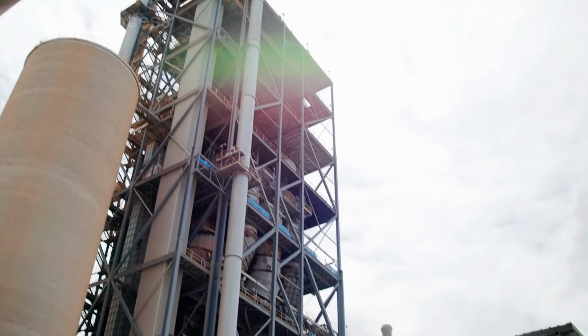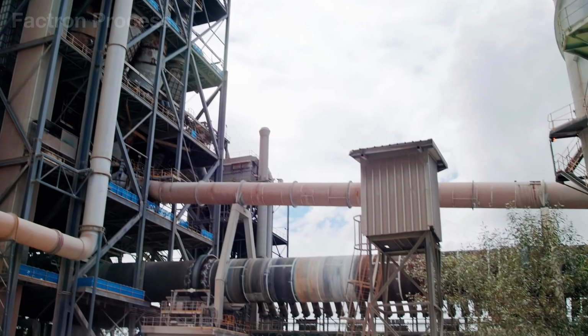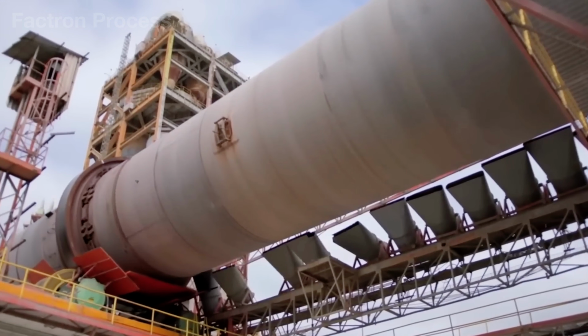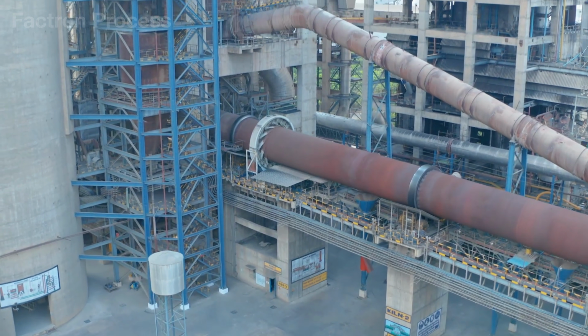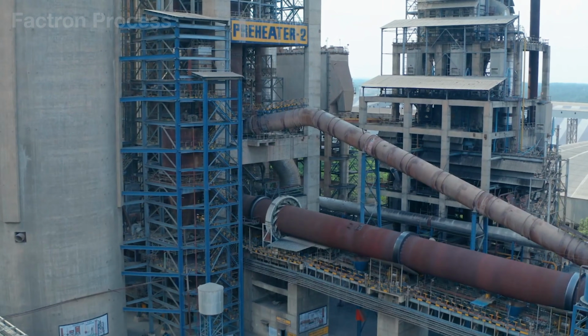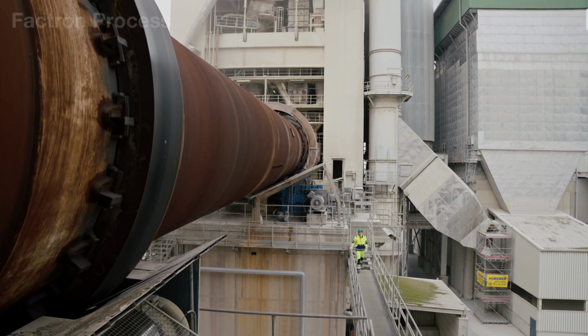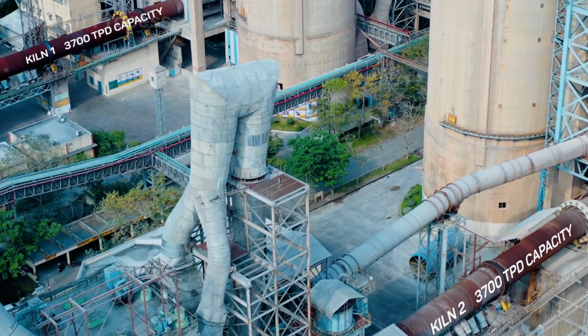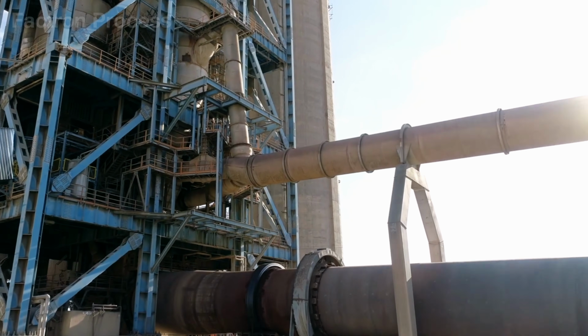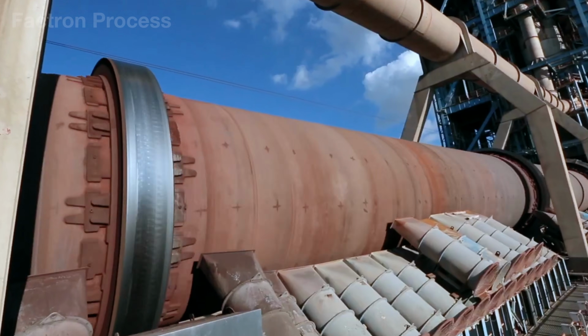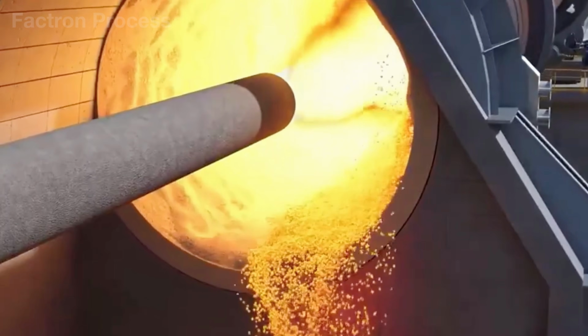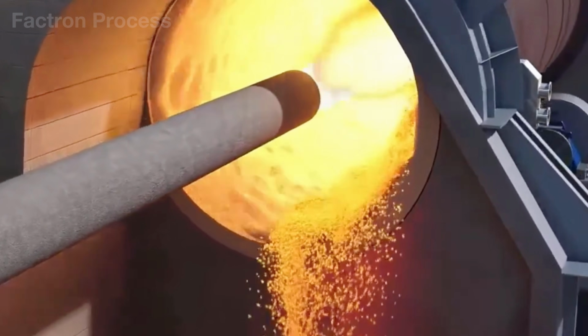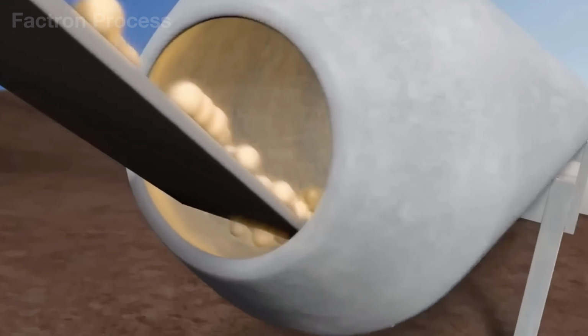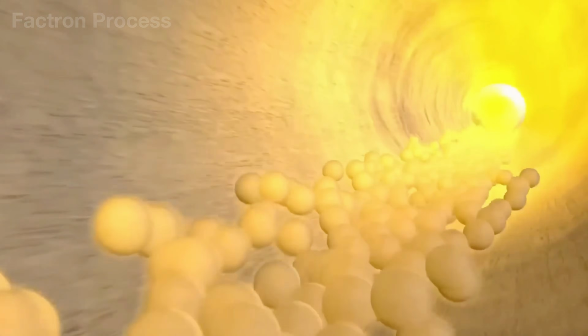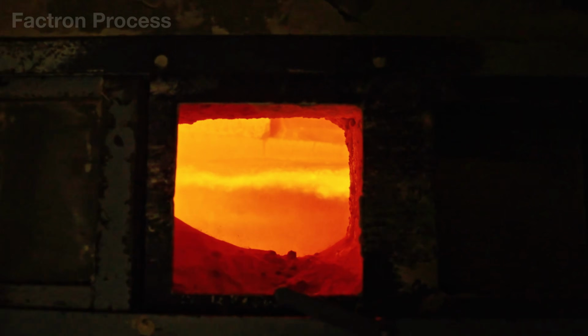Leaving the calciner, the raw meal enters the hottest part of the entire plant, the clinker kiln. This massive cylindrical steel shell can extend nearly 260 feet in length. Lined with refractory bricks, it is installed at an incline of roughly 2.3 to 4 degrees and rotates slowly at speeds ranging from 0.6 to 4.5 revolutions per minute. As the kiln turns, the material gradually moves from the higher end to the lower end, advancing deeper into a thermal zone exceeding 2,700 degrees Fahrenheit, while the flame at the burner can reach temperatures of around 3,600 degrees Fahrenheit.